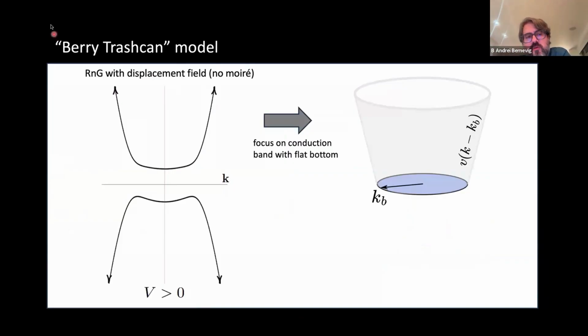Now, there are also very interesting developments in rhombohedral graphene from Long Ju's group and Xiaobo Lu at Peking. But basically, what I want to argue is that this system is completely not understood so far, and it's very new, unlike any other of the fractional Chern insulators, because this system actually is gapless. So it's not just a band like a Landau level, where I fill it at 1/3, but I have a flat band at the bottom, and then a gapless region of states, and the fractional Chern insulator is still seen at a fractional filling of this bottom. This system is completely not understood, and hence there's room for theoretical development here also.